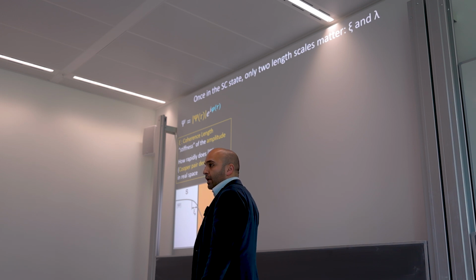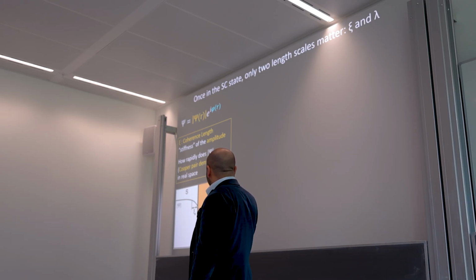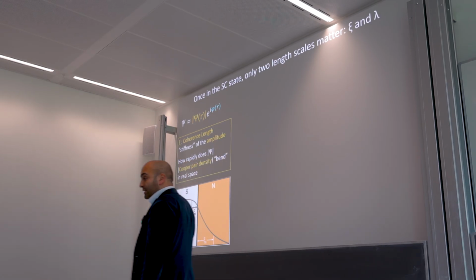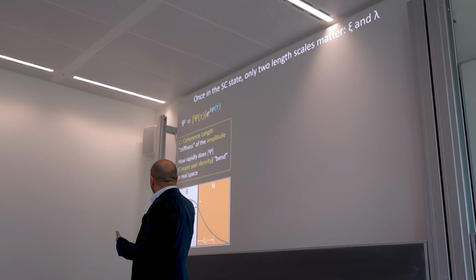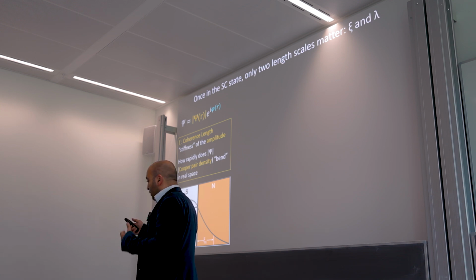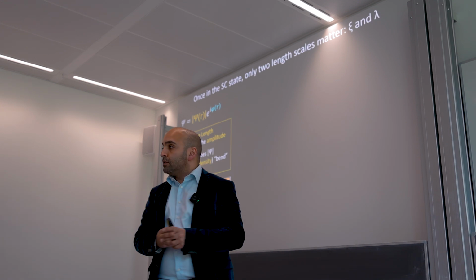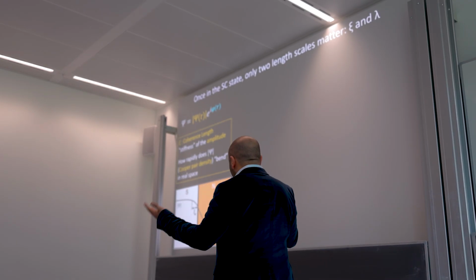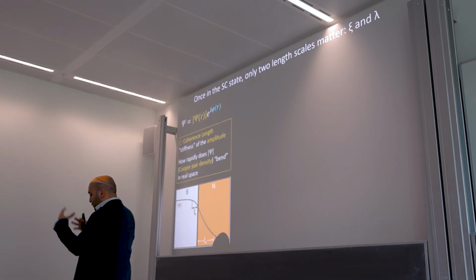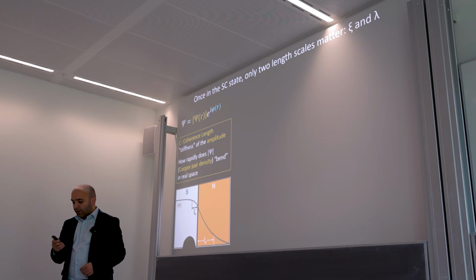Eventually, this thing has to be metallic, otherwise everything would be superconducting. So here your amplitude is 0, and here it is maximum, and you see this length scale over which your order parameter decays. That's your coherence length. And it's material dependent. For instance, in a superconductor your coherence length is different from the coherence length in a normal metal. So that's what a coherence length means. Any questions? This is all clear? Good. So this deals with how stiff the amplitude of your order parameter is.